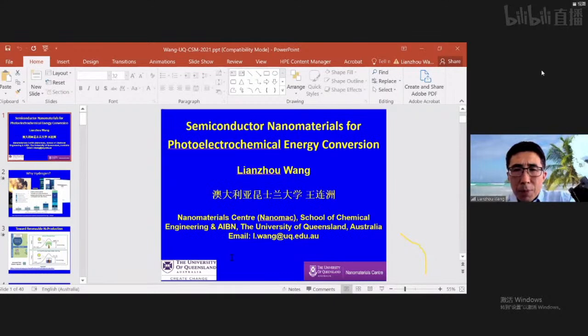As I said, this perovskite material has a much larger light absorption coefficient compared with the others. So this is one thing, and the other thing I think is the charge injection performance, because this one has very good light harvesting and charge separation and transfer properties, which will help. But the difficulty is the stability of the material. In this case, we use a gas solid phase reaction. But more recently, we have developed a new approach to immobilize the perovskite into some composite, like a MOF composite, which certainly has much better stability, putting it in water for 10,000 hours and it still has the capability.